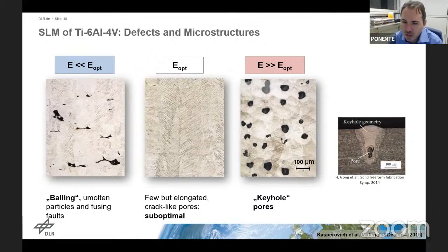Many studies of this kind on a variety of materials, from aluminum alloys to steel and others, typical porosity studies, where you generally find that if you have too low process energies, below the optimal energy, E-opt, then you get the typical balling effects, meaning you have too little energy, the material doesn't melt entirely, and you get these unmolten particles in the material that leave these very sharp, edgy cracks. And you see at the bottom of these round shapes here, you can still guess it's powder particles that are not sufficiently molten into the material. That's on the low energy side.